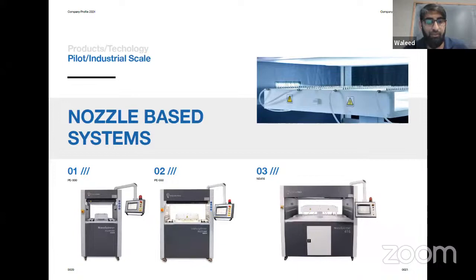Here you have our pilot scale nozzle-based systems. In these nozzle-based systems, the main difference is the substrate size on which the production is going on. For example, if I'm talking about PE 300, the 300 means substrate size is 300 millimeters, which can be effectively coated. As you change the scale, going up to 550 means 55 centimeters or 550 millimeters, you are increasing the number of nozzles that are electrospinning onto the substrate. And this overall increases your production capacity. Same, with NS416, you can increase even more.